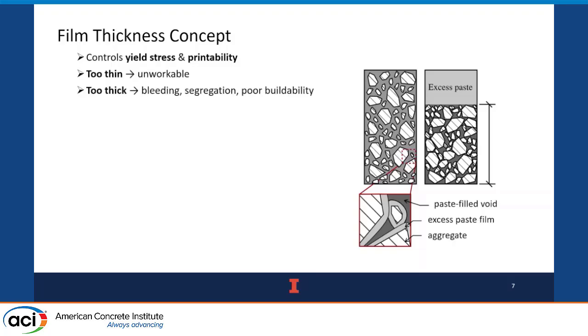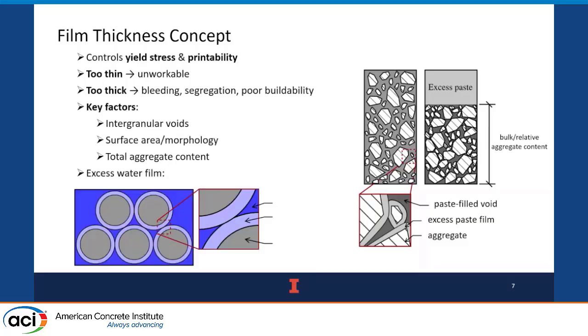So this idea of working with a mix where you think of the aggregate system as solid particles, and then the cement is coating those particles, and that's the film. The thicker the film, that's what's going to ultimately start to really change your workability. If it's too thin, it becomes unworkable. If it's too thick, all of a sudden you get bleeding, you get segregation, things like that. And yes, we acknowledge that the film has its own rheological properties. So if you go to high water cement ratio versus low water cement ratio, that's going to change how this film interacts within the whole system.